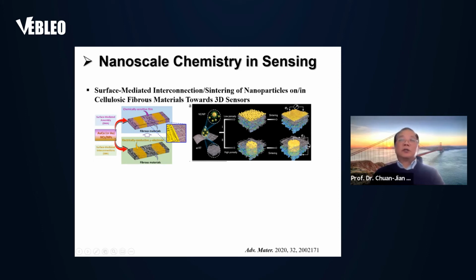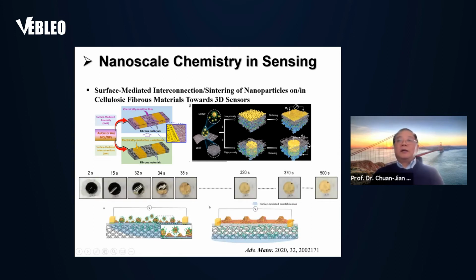So in this process, you can sinter the metals on the surface of the fibrous materials, or you can penetrate across the fibrous materials, because they are highly porous, which allows you to do that. So here's one in situ capture of the surface morphology. From left to right, as you drop the nanoparticles on the surface, it is black. After about 30 seconds, it's almost golden in color. And then over a prolonged time, it's a golden color, much shinier.